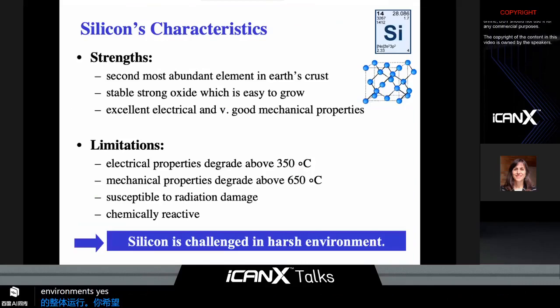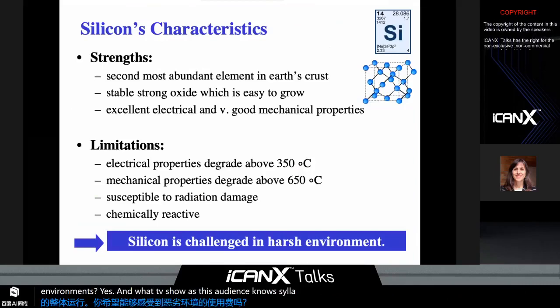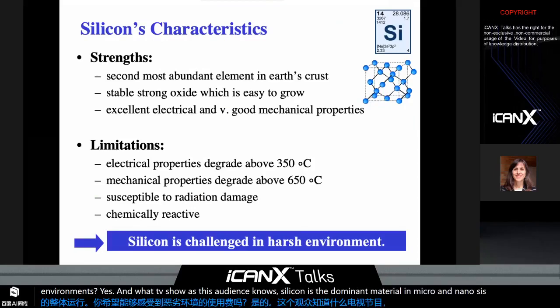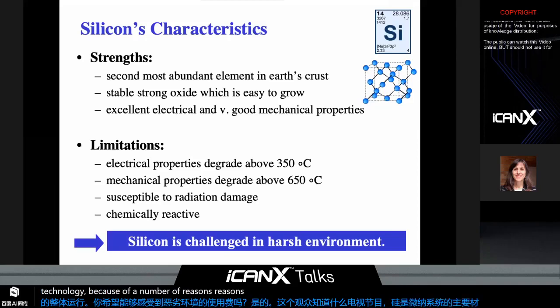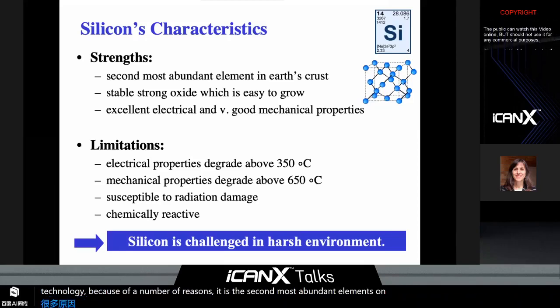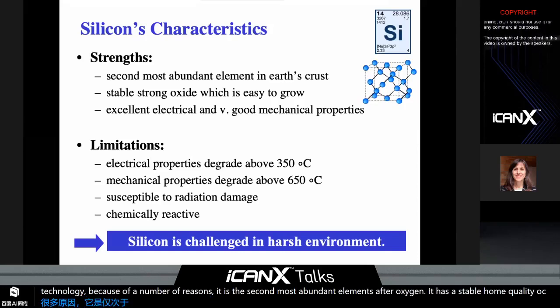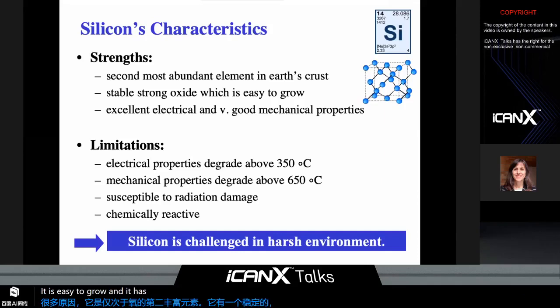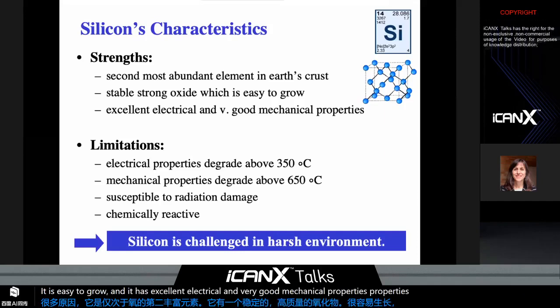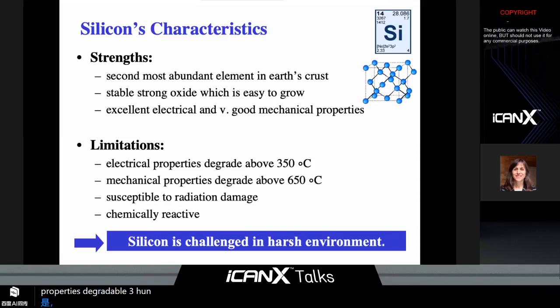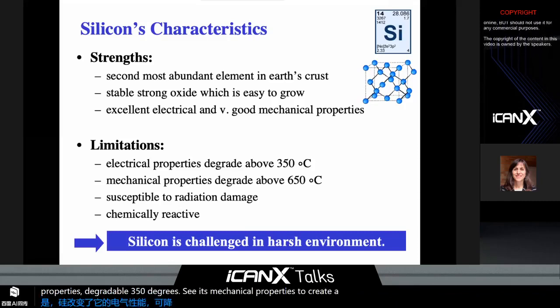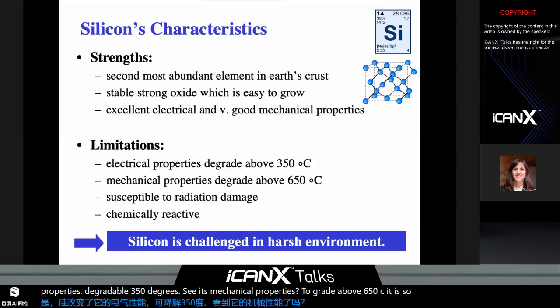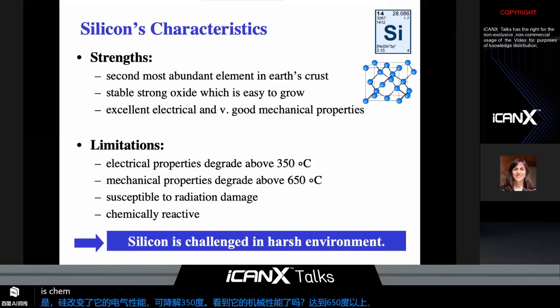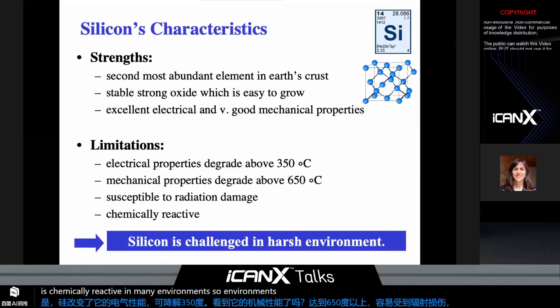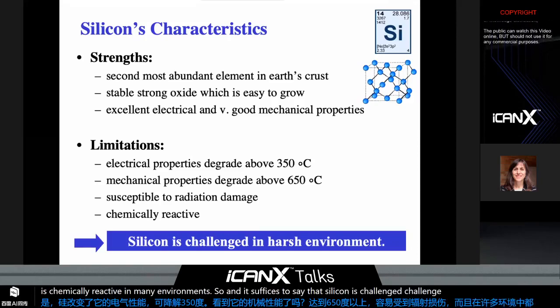That's the motivation. As this audience knows, silicon is the dominant material in micro and nanosystems technology because of a number of reasons. It is the second most abundant element after oxygen. It has a stable, high-quality oxide that is easy to grow, and it has excellent electrical and very good mechanical properties. However, silicon has limitations. Its electrical properties degrade above 350 degrees C. Its mechanical properties degrade above 650 C. It is susceptible to radiation damage, and it is chemically reactive in many environments. So it suffices to say that silicon is challenged in many harsh environments.